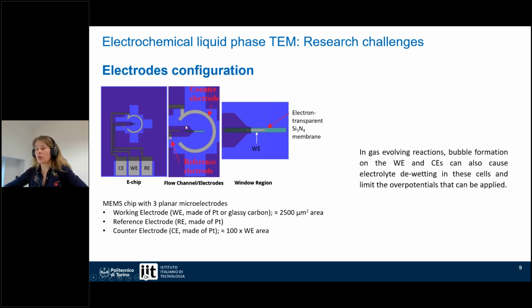Then we have the reference electrode. The reference electrode is made of platinum. It's in here. It will possibly be a source of uncertainty because it is highly sensitive to the chemical environment and to different dissolved gases. And the last electrode, the counter electrode, which is sitting here, is also made of platinum, and it can generate gas, and therefore it can be a source of reductive or oxidative species that might come into the working electrode area and interact with the sample.